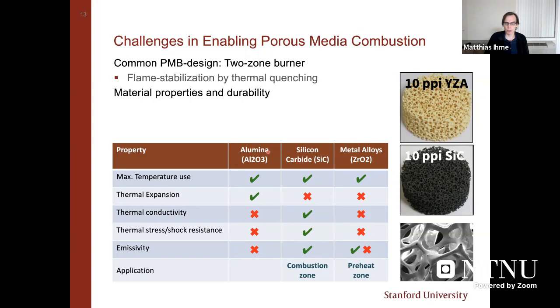What I'm plotting is 3 different material properties of the ceramic porous foam. In the previous slide, I showed you mostly silicon carbide porous foams, but there are different materials that we can utilize. And this is, for instance, alumina, silicon carbide, and metal alloys in the form of zirconia oxides. And as I said, a key aspect of these porous media burners is this very strong coupling between the combustion process, the heat release, and the heat recirculation.